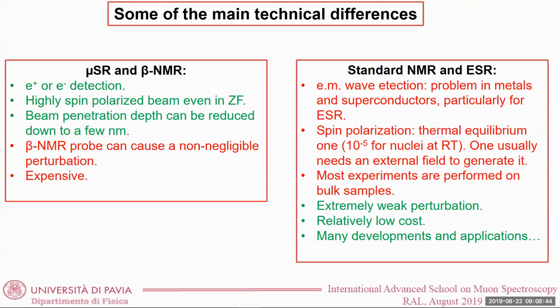Of course, there are many techniques that can help to improve this even in nuclear magnetic resonance. And the other point is that if we want to produce a polarization in an NMR experiment or an ESR experiment, we need to apply a magnetic field. While in MUSR or beta NMR, you already have the 100% in MUSR polarization of the muon spin, even without applying an external magnetic field. And this allows you to perform the zero field experiment quite conveniently. So these are two main points where these two techniques have some advantage.